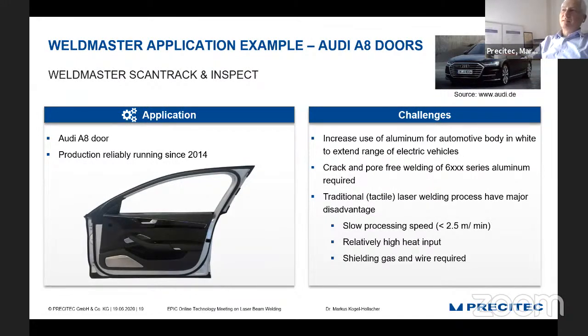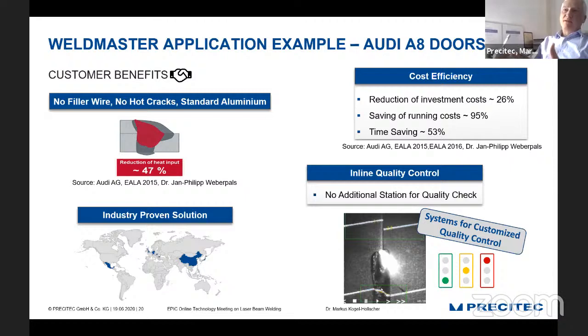So this is also 6,000 series, and by oscillation of the laser beam, we can also do some pore-free and crack-free welding. And what is very important, there is no additional material, no filler wire needed in that application. So these are the customer benefits which come with that application, which was presented several times by Mr. Weberpals from Audi, with the use of the oscillation and with getting rid of filler wire. There is a heat reduction of 47%. The reduction of the investment cost is quite remarkable. Running costs can be saved, and there's a lot of time saving. And additionally, by using the inline control of the Weltmaster system, there's no additional station needed for a quality check.